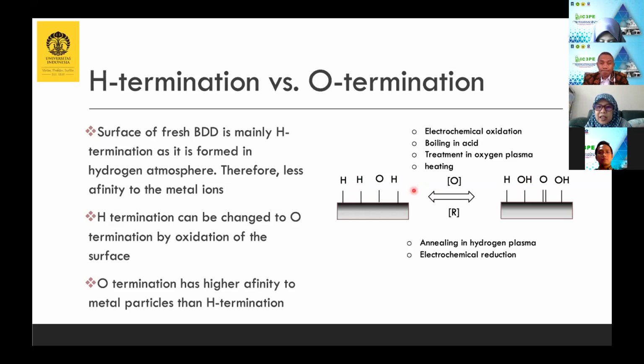How can we oxidize the surface? We can oxidize by using electrochemical oxidation. Of course, we apply a high oxidation potential on the surface of diamond, and this surface will be oxidized to oxygen termination. We can also boil it in acid solution, and it will be oxidized also. We can treat it in oxygen plasma, putting it inside the oxygen plasma. We can also heat it at very high temperature, which will oxidize the surface of diamond.